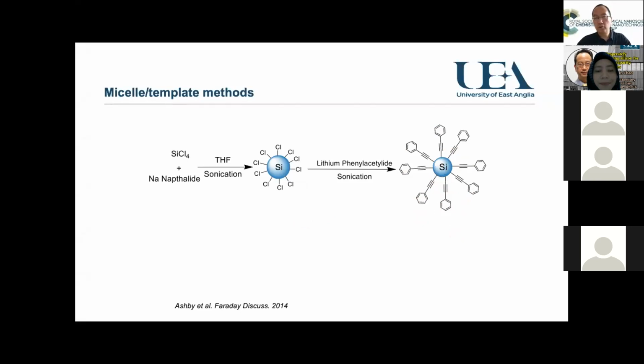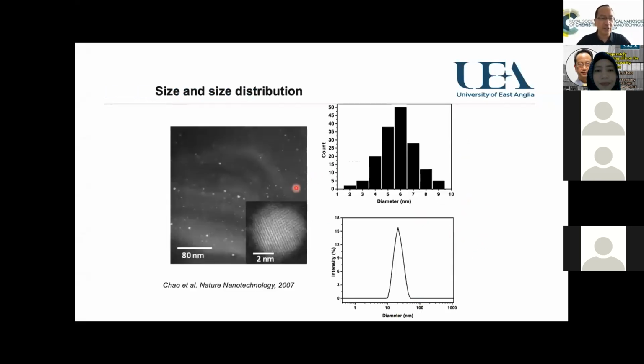I'll talk a bit about characterization again. After the synthesis, we need to measure the size of the materials as well. For the bottom-up method, we really need to confirm whether the silicon nanoparticles still have crystalline structure inside. That's important for our applications. We looked at TEM and confirmed that the structure still has this crystalline structure, and the size is within a few nanometers.